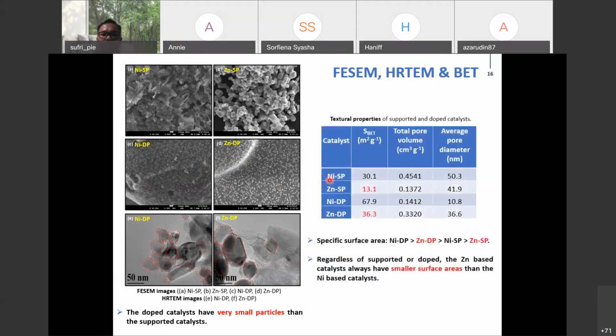This finding is in agreement with the surface area from the BET analysis. The doped catalysts, nickel DP and zinc DP, have a larger specific surface area than the supported catalysts. The smaller the particle, the larger the surface area. Regardless of support or dope, the zinc is always lower in surface area. But later, when we see the catalytic reaction, surprisingly, the zinc-based catalyst performs better compared to the nickel-based catalyst.